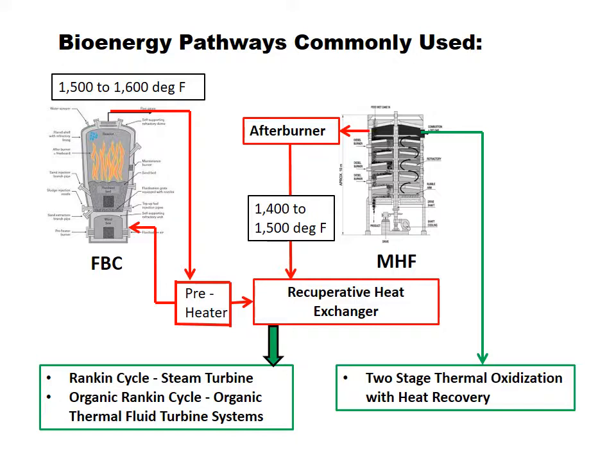The multiple hearth, because it dries in the upper zones, picks up undesirable contaminants in the drying phase. So you have to put in an afterburner to burn out these VOCs that were stripped out in the drying stage. The afterburner is basically just a refractory-lined vessel with a burner in it, with a couple seconds detention time. That heats it up to 1500 degrees to destroy the VOCs. That could then be taken again to the recuperative heat exchanger into a steam turbine or organic Rankine cycle system. But the multiple hearth offers another option, and that is two-stage thermal oxidation, where we come right out of the furnace.